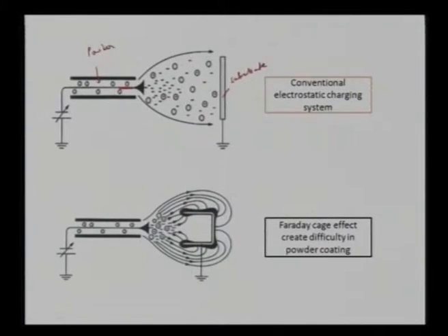So we have a particular electrode. As powders are passing through it, they get charged. Once the charge is created on the powder particle, it is at higher potential, and then it progresses to the lower potential side. We can have some fans or blowers which allow the particles to attain a certain velocity, or basically to flow from the gun to the substrate.